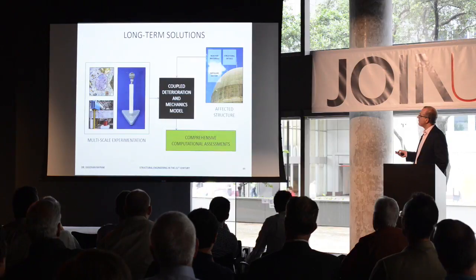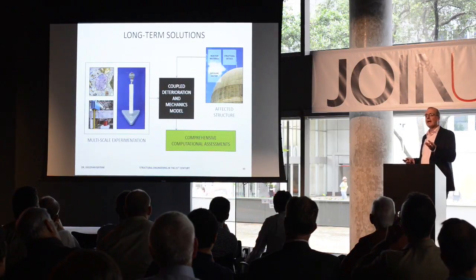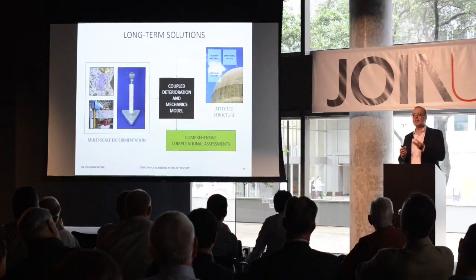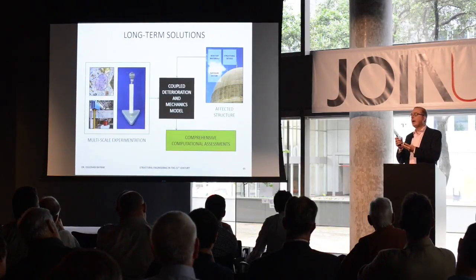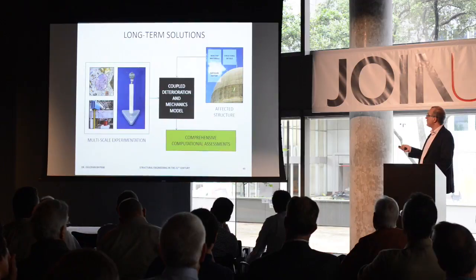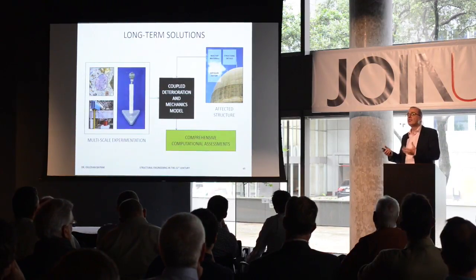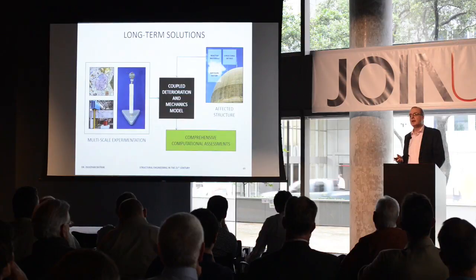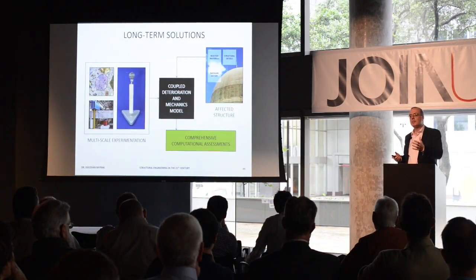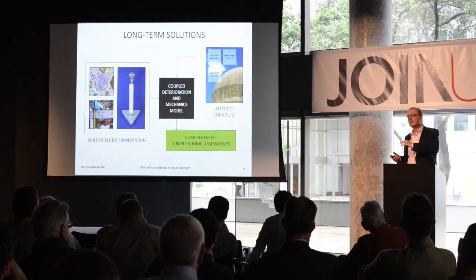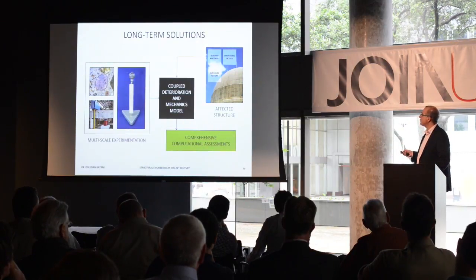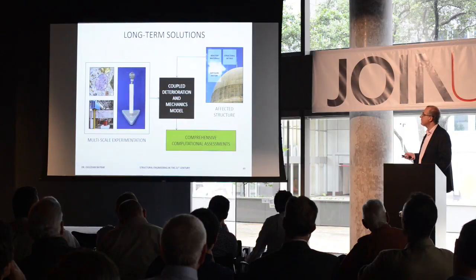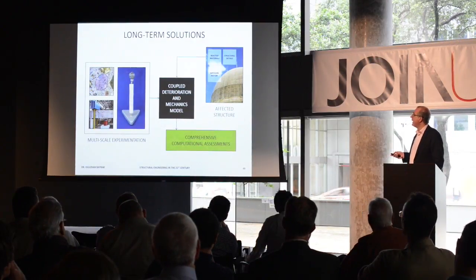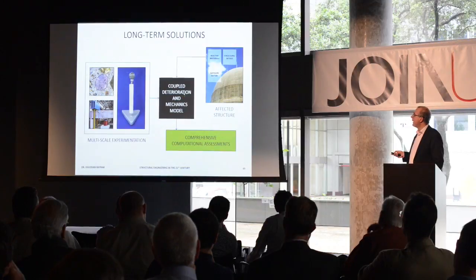And you start looking at a real structure. For the ASR reaction to take place, we need three basic elements, right? We need the reactive aggregate, we need a high alkali pore solution, and we need the presence of moisture as well, right? So if you take a look at an existing structure, portions of that structure may be exposed to elements, and therefore moisture may be present. Other parts are protected, therefore moisture isn't there. So all of that information and the local conditions need to be fed into that mechanics-based model. And degradation certainly has to be modeled.